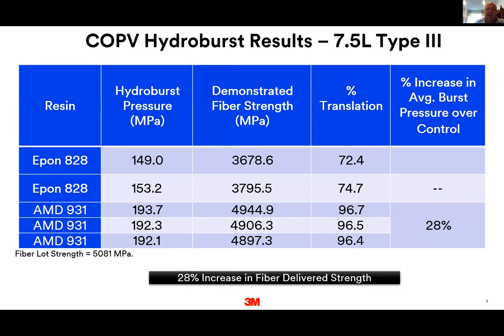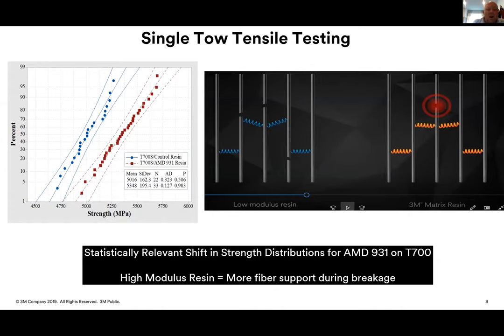Well, what does this mean for tank design? And what's going on with the fiber? What we feel is happening, and we've looked at this from single-tow tensile testing, is that we shift the entire strength distribution on T700, for example. What we've schematically shown here is that we are using a high modulus resin to support the fibers. When the fibers start to break, there's more support given by the high modulus resin. That's what allows you to get more fiber-delivered strength out of your fiber. It's more efficiently using the fiber-delivered strength, and it's improving load transfer.